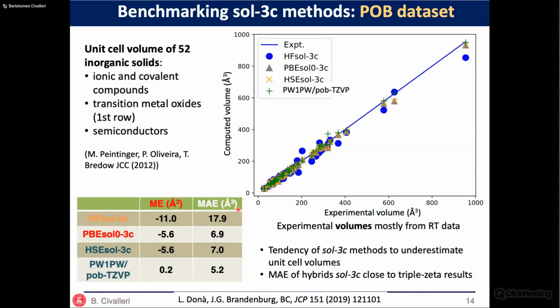The other point is, can we really extend the calculation to solid state systems like inorganic solids, covalent solids? These are results for a set of 52 inorganic solids taken from this paper, in which the authors proposed what is called the POB triple zeta valence basis set. We repeated the same calculation with our composite method, and we get results that are comparable with this triple zeta quality calculation with respect to the mean absolute error, as you can appreciate from this picture, even if there is some tendency of this method to underestimate the unit cell value. But overall, the results are good.